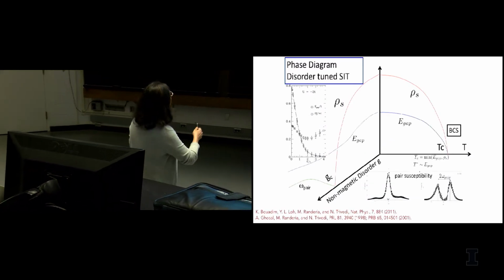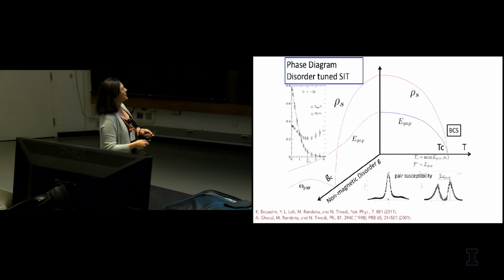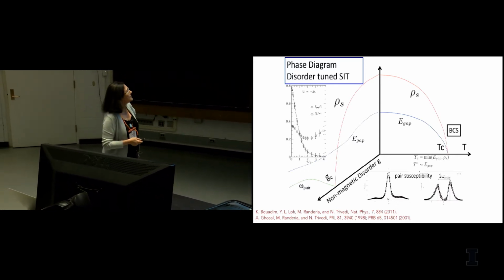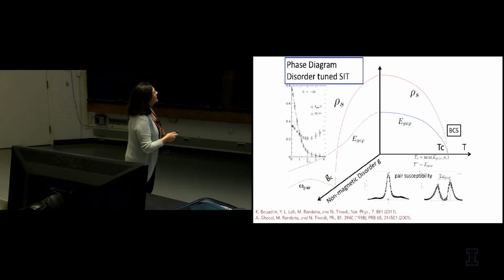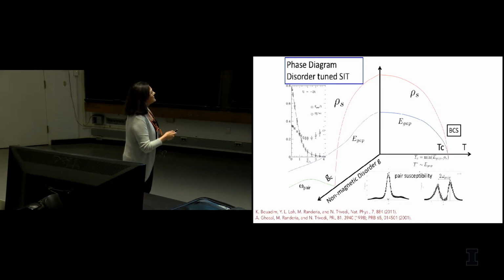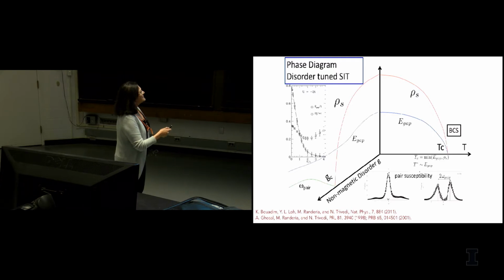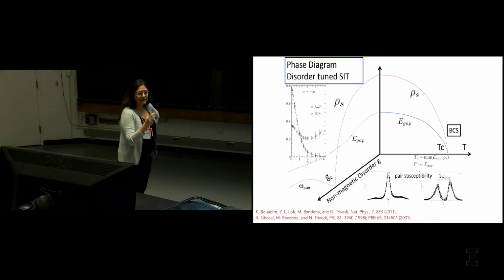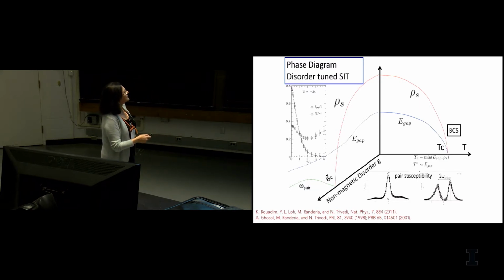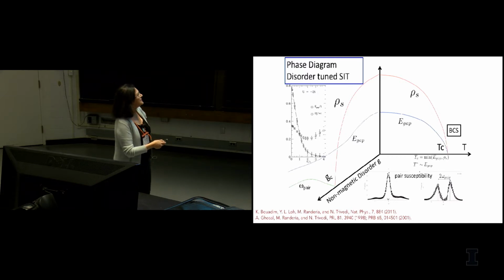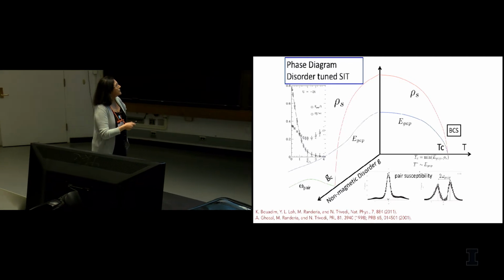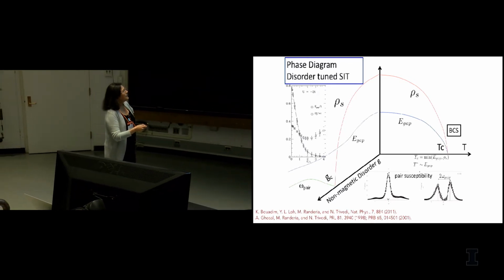And I have summarized it here in this sketch, but all of this is backed up with several calculations. What this shows here is an energy scale as a function of temperature, and what you see is the standard BCS paradigm where the gap and the superfluid density, measured in some mutual inductance experiment, both vanish at Tc. So this would be the standard BCS paradigm. But when you add disorder, what you see is that the single particle gap remains finite for arbitrarily large disorder.